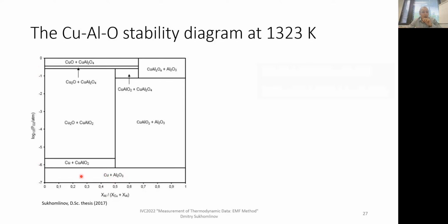And then when we have a lot of copper, the equilibrium phases are, for instance, at 10 to minus 6, metallic copper and delafossite. If we have more aluminum in the system, then it's going to be delafossite and alumina. And with increasing oxygen partial pressure, phases change. So copper, Cu2O, and then delafossite has a rather wide stability range in terms of PO2, but when we exceed it, then spinel becomes stable.